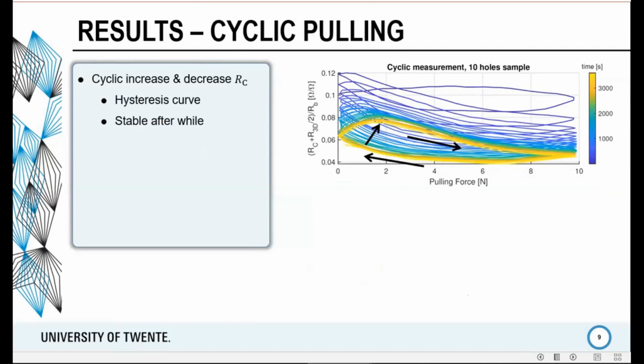So first, you notice some drift. So we were cycling, and you notice that there's some drift in the sensor. But then after a while, you get this stable cycle where first, upon pulling, the resistance increases a bit, and then it goes down. And when you release it, it again goes to the 0 force, the 0 newton value.